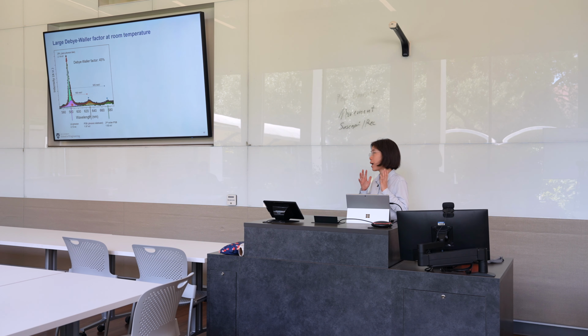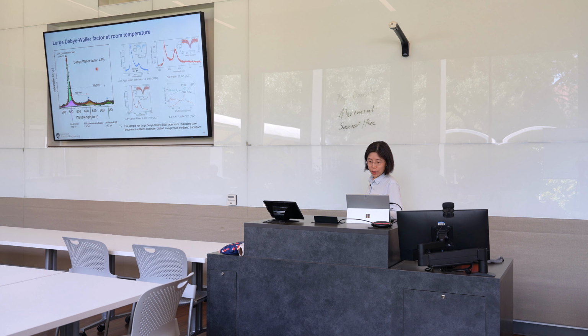So now if we calculate the area under each of the peaks, we get our Debye-Waller factor, the percentage area under the ZPL, which is about 45%. This is actually a pretty high value for single photon emitters in boron nitride at room temperature. Now if we compare this to several other single photon emitters in boron nitride reported in the literature, you can see their phonon sideband is quite comparable with the zero phonon line, indicating a much smaller Debye-Waller factor. So our Debye-Waller factor is much better.